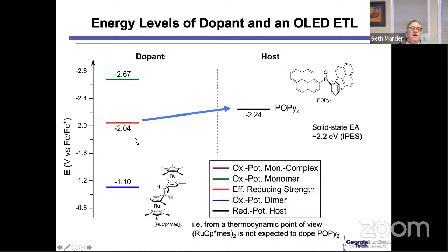So what we have to do to figure out the thermodynamic potential is to subtract essentially, for each half of the molecule, half of that bond strength, okay? And when you do that, and this was calculated, and we benchmarked those calculations against the cases of other systems where we could measure an equilibrium between the monomer and the dimer, but that's another story, okay? You calculate that the thermodynamic potential of this molecule to reduce this is negative 2.04. So this is still uphill by 0.2 of a volt per POPY2.